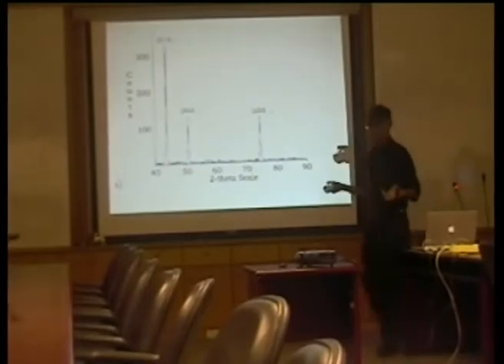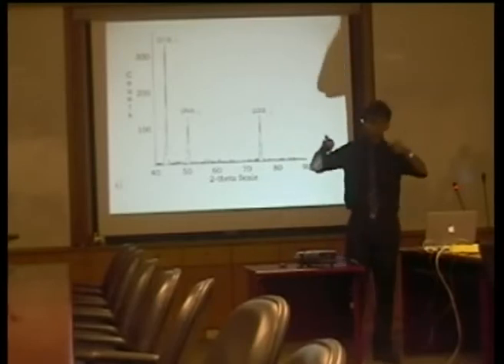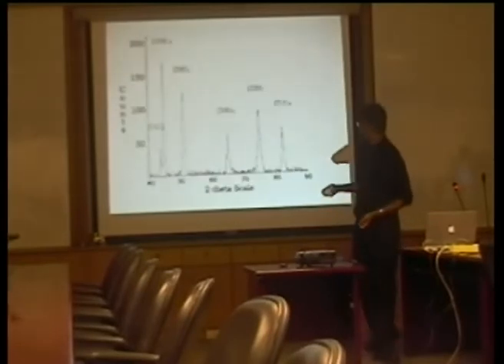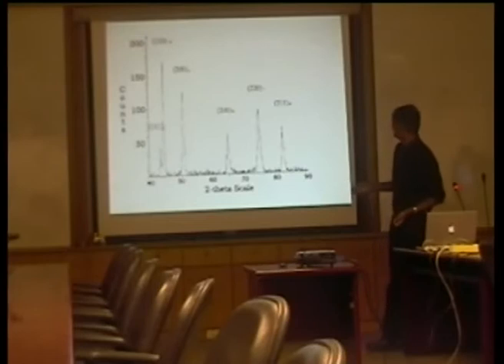This is the X-ray diffraction pattern before the deformation. You can see it's fully austenitic material. Yeah. Even though thermodynamics will tell you it shouldn't be austenite. Yeah, 316L shouldn't be austenite at room temperature. But it's because you cool it sufficiently rapidly, you make it fully austenitic. After deformation, you get these lines due to the martensite forming.